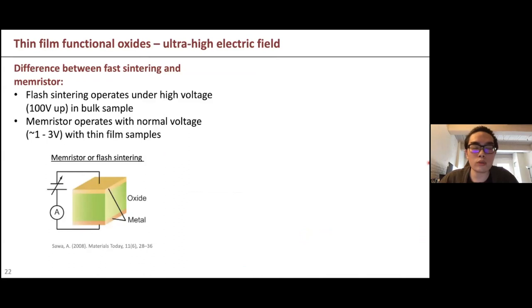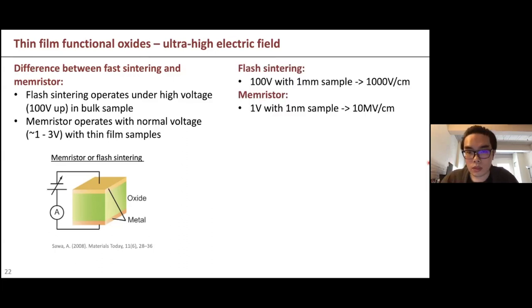For flash sintering, usually you apply a very high voltage, at least 100 volts and above, to make it happen. For a memristor, usually the operation voltage is comparably much lower than 100 volts. It's usually like 1 volt, and I think above 2 or 3 volts is considered quite high. So what's the difference between these two? Even though for flash sintering the voltage is very high, the sample is considered a bulk sample that you can hold with your hand.